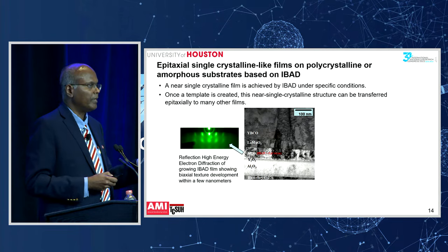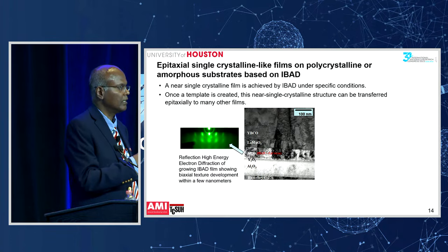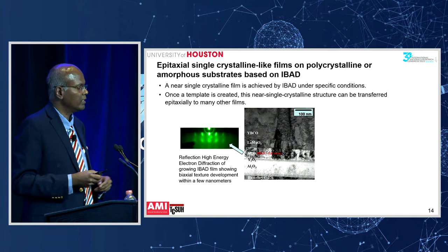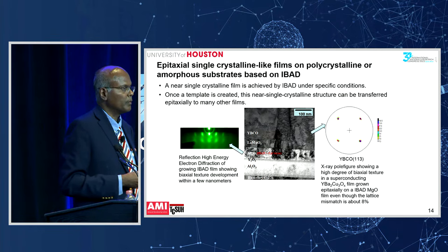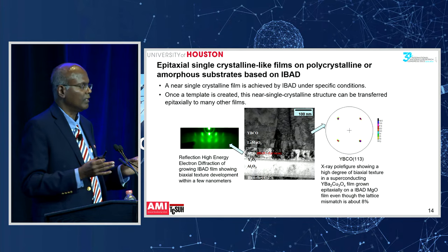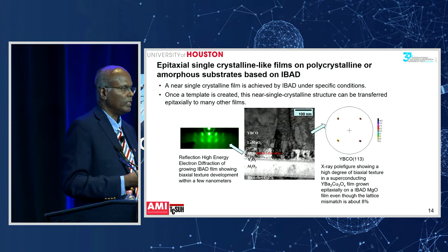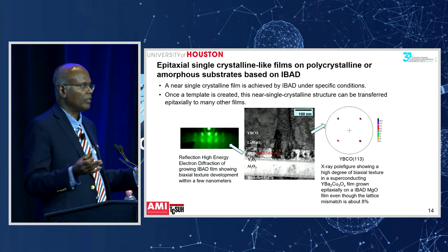We have grown oxides, nitrides, silicides, arsenides, metals, all semiconductors, all kinds of films epitaxially using this technology. Here we're using mostly oxides. If you look at, in this case, a superconductor film grown on this kind of substrate, you can see the X-ray pole figure looks like a single crystal material. It's not. It's actually a polycrystalline material. But now the grain-to-grain misorientation of the superconductor is only 2 degrees. So like I showed you in the previous chart, if you have grain-to-grain misorientation within 2 degrees, then the current carrying capacity is not affected.